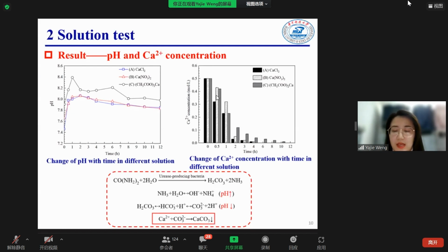And we can see calcium ions decrease over time. The reason is that carbonate ions form from the hydrolysis of carbonic acid, and calcium ions form calcium carbonate precipitates. So calcium ions are continuously consumed and generally reduced. And we can see calcium chloride decreases the fastest, and calcium acetate decreases the slowest.